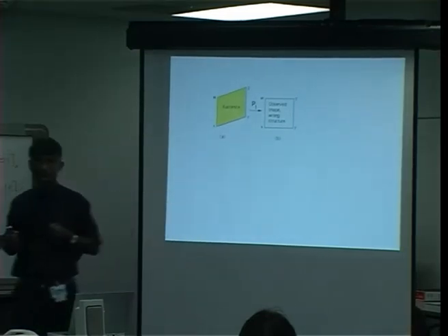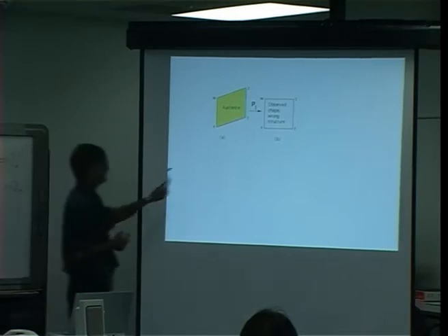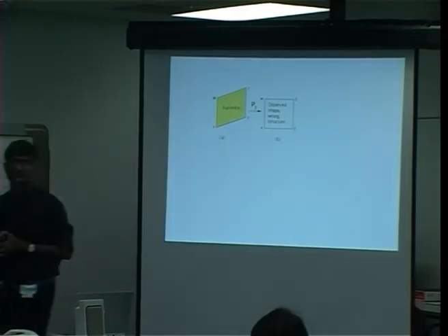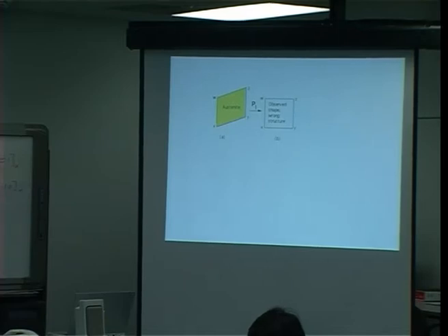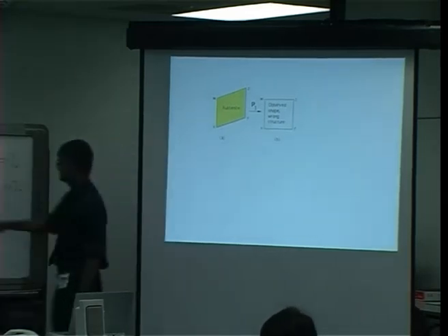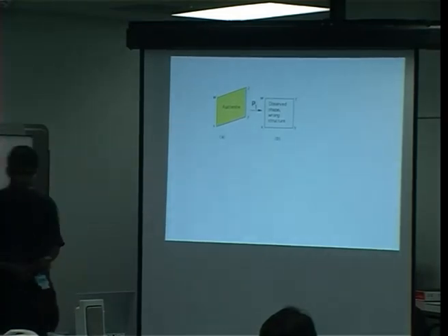But of course, an invariant plane strain cannot produce ferrite. We've demonstrated that the deformation which takes austenite into ferrite is an invariant line strain. Therefore, if I apply the observed shape change to the austenite, I produce the wrong crystal structure, because you cannot have a shear deformation changing austenite into ferrite. So the observed shape change is inconsistent with the deformation which takes austenite into ferrite.